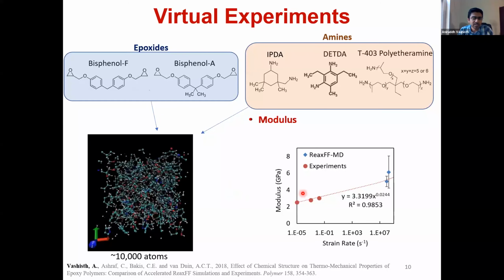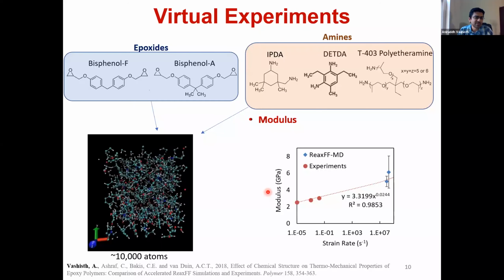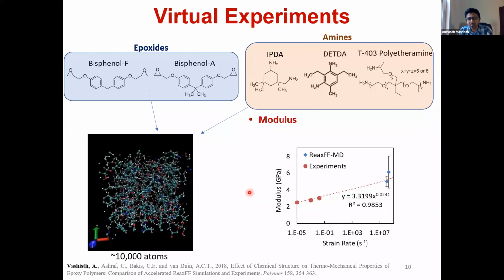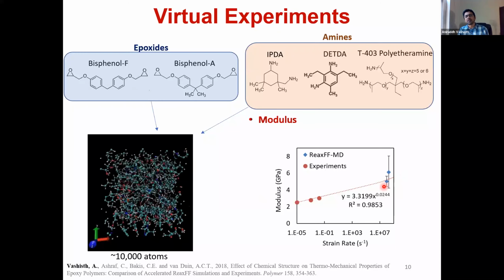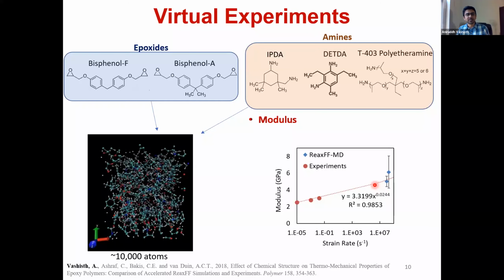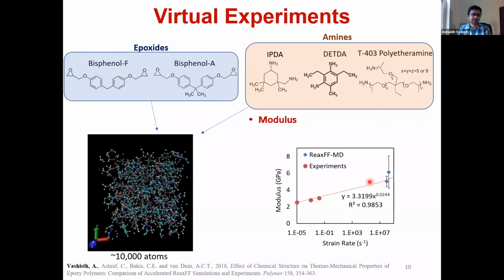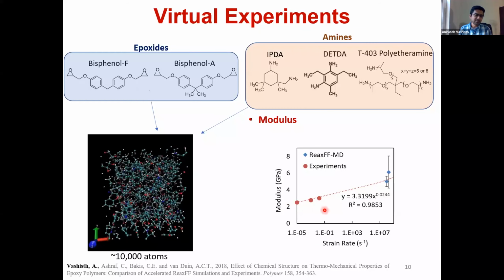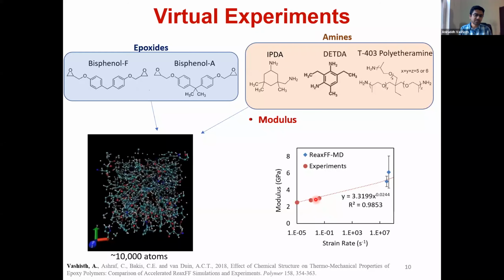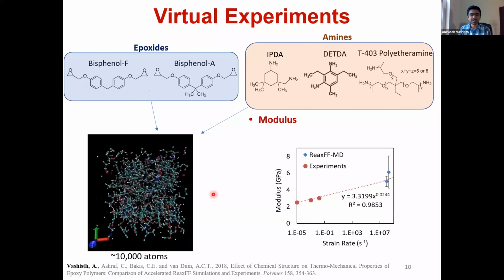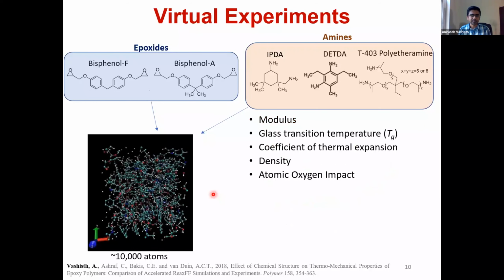Usually, you have to complete your simulation within a couple of nanoseconds for molecular dynamics. So we have to do virtual experiments at really high strain rate. But we did some experiments as well at lower strain rates, and if we extrapolate our results, we see fairly good agreement. Some of the other virtual and physical experiments that we did were TG, density, coefficient of thermal expansion, and we see a pretty spot on comparison between our experiments and the simulation.